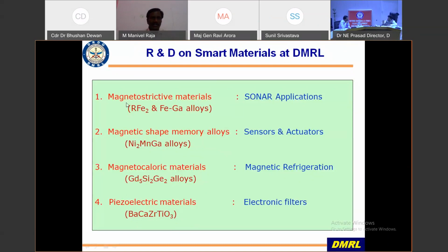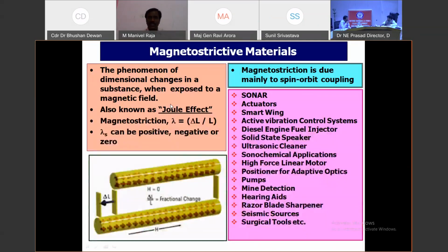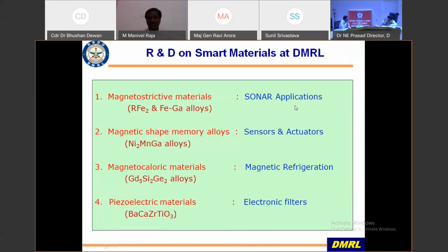The first one is the magnetostrictive material. This activity was taken up for the development of a sonar device for the Navy. Here this magnetostrictive material will replace the piezoelectric material. The current technology uses a piezoelectric transducer in the sonar, but sonar using piezoelectric material works at very high frequencies. In order to reduce the frequency of operation, the idea is to use the magnetostrictive material, which can be used at very low frequencies, about 1 to 2 kilohertz. By reducing the frequency, we can increase the range. That is the advantage of magnetostrictive smart material.